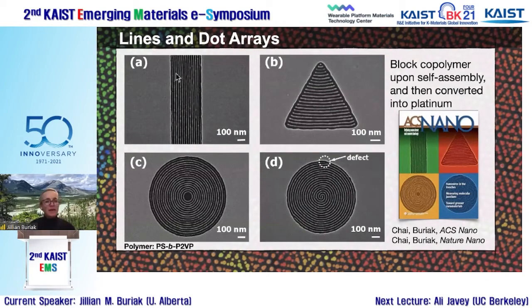So in the top left, for instance, you can see we're forming wires. These are all platinum in this case. These are formed inside of trenches on a piece of silicon that we actually etched in using e-beam lithography and a simple anisotropic etch, about 30 nanometers deep. The block copolymer goes into these trenches, and when it undergoes self-assembly, it adopts the lowest energy configuration, which is one which has long-range alignment down this trench.